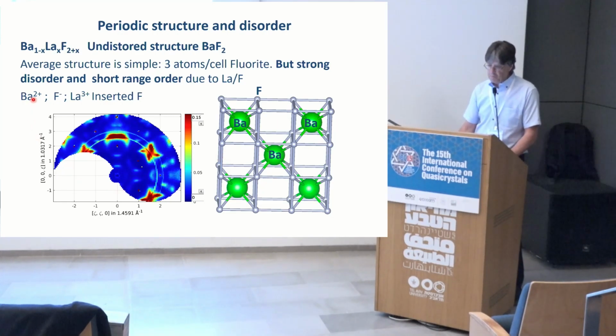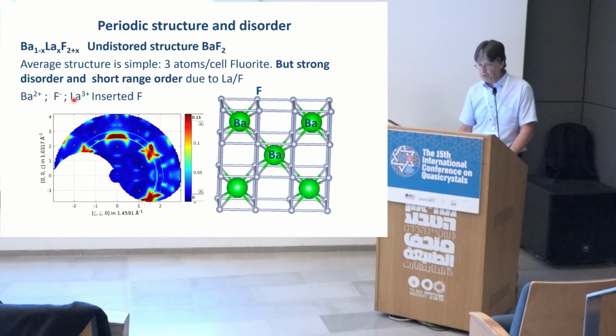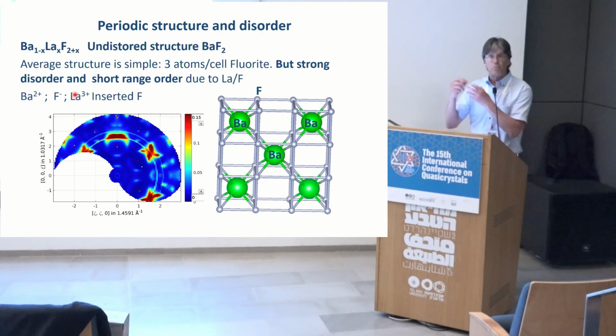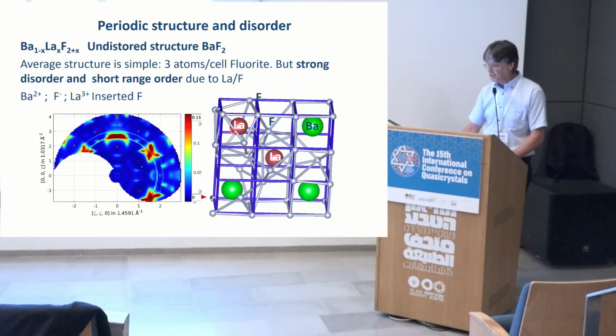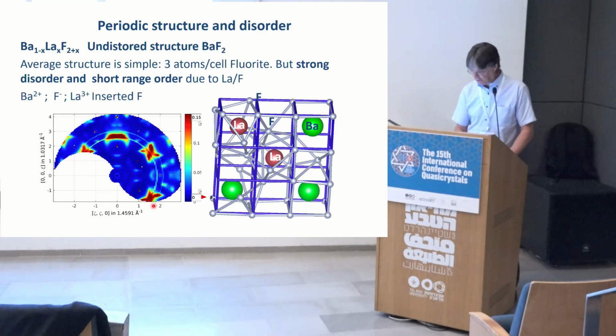So we substitute barium 2+ by lanthanum 3+. There is an electronic balance. We have 2 fluorine for 1 barium. If we put lanthanum 3+, we need to put 1 more fluorine. And what's going on is this here. And you see that you have substitution of lanthanum here, a strong new fluorine site occurring, and a strong distortion around your lanthanum. And because of this distortion, we have the signature here, which is the diffuse scattering.